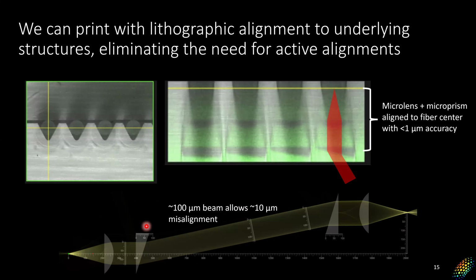I think I have a slightly old slide here. What's missing here is, imagine that there is a fiber end here, and then the scaffold is around this structure. And then you have these components printed in polymer inside of that scaffold. That's one thing. And then you have just air. And then you have another fiber or PIC over here and another scaffold. And so the output of each of these is this several hundred micron beam going in some direction, right? As long as you line these up properly, this expanded beam will then be received here. It'll be straightened out and then focused back down to couple into the PIC or fiber on that end from the PIC or fiber on this side.